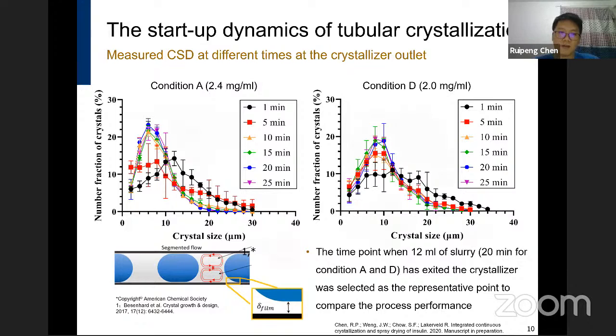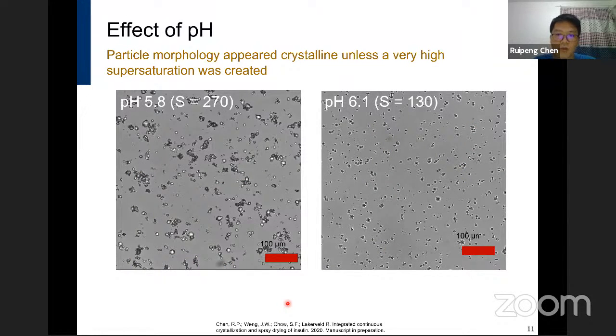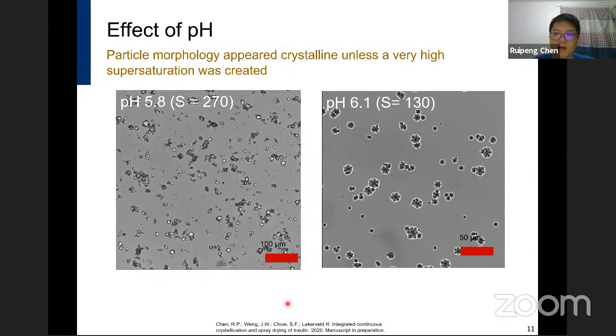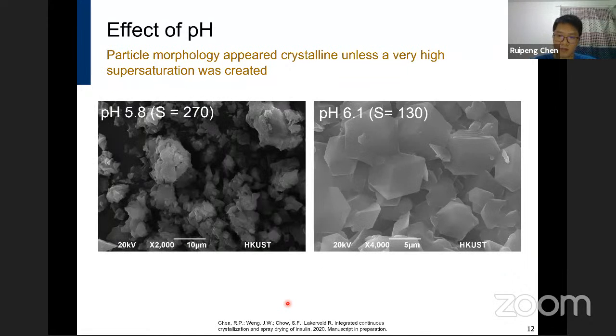So first, we can look at the effect of pH on the particle morphology, and two pH values were tested. One is pH 5.8, which has a very high supersaturation. The other is pH 6.1. Most of the particles obtained at pH 6.1 show the typical crystalline shape of insulin crystals, the rhombohedral shape. This is more clear if we look at the microscope images with a higher magnification. While for the particles obtained at the lower pH, which has a very high supersaturation, a large number of the particles appeared amorphous, and agglomeration can also be observed. The particle morphology is also consistent if we look at them on the SEM, as you can see in these two images.